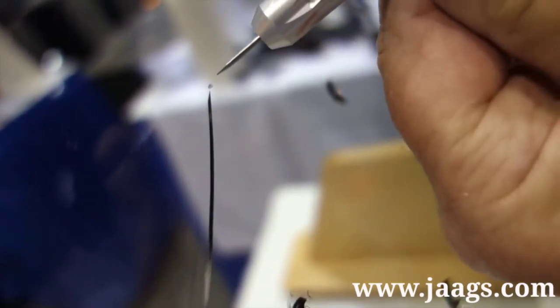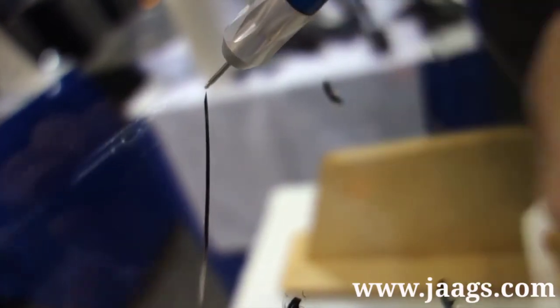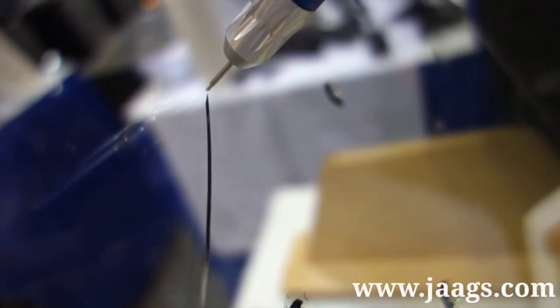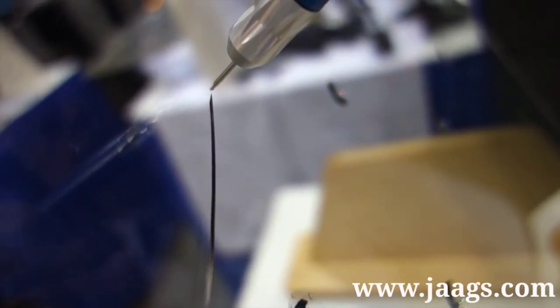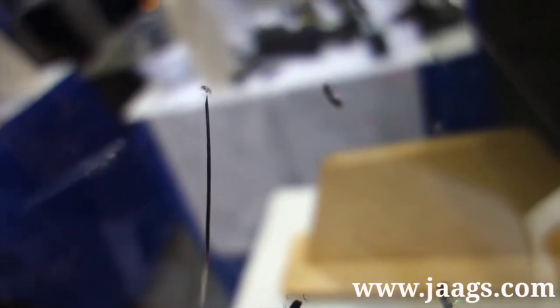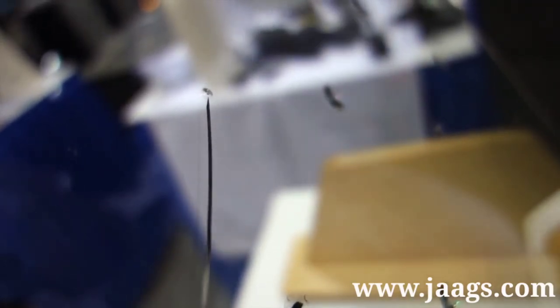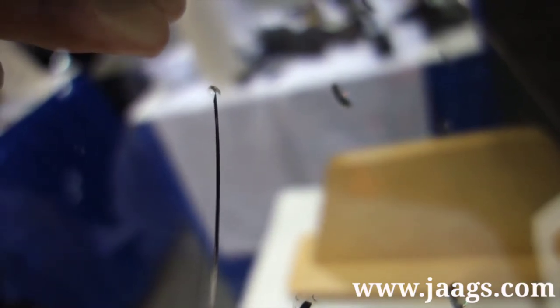He will insert the spring hammer into the drill hole and create a mini bullseye. Make sure the spring hammer is perpendicular to the glass with the point of the tool pressed firmly in the bottom of the drill hole. He will apply light pressure to the glass so the crack runs into the bullseye that has been created.